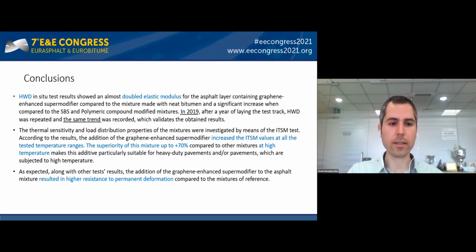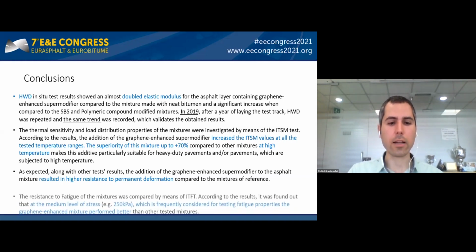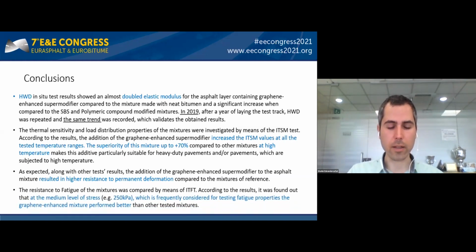As could be expected, the testing results for permanent deformation showed better results for the mixtures thanks to the presence of graphene nanoplatelets in this mixture. And finally, the resistance to fatigue of the mixtures was compared by means of ITFT.